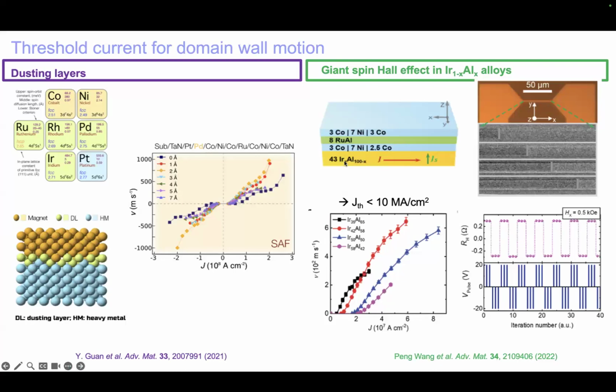Instead of using platinum, we found that there's a certain family of materials, in particular, let's say iridium and aluminum, that form the so-called L10 structure, in which even at room temperature, it will form a perfect atomic layering structure with a layer of iridium, a layer of aluminum, a layer of iridium, a layer of aluminum. It's fantastic. And this happens for a large family of these materials.